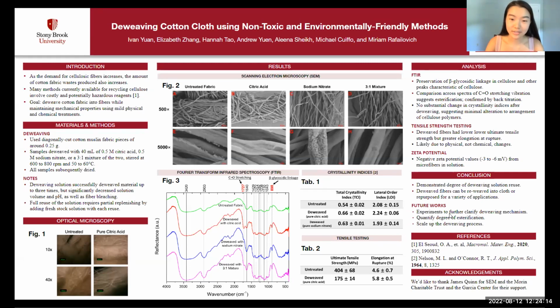Using scanning electron microscopy, or SEM, as shown in figure 2, we observe that the structure of the fiber bundles is mostly preserved. However, the fibers are also rougher after deweaving, pointing to fiber structure alterations that may impact mechanical strength. The Fourier transformed infrared spectra, or FTIR, shown in figure 3, resemble cellulose spectra in literature and suggest the preservation of the beta-glycosidic linkage.